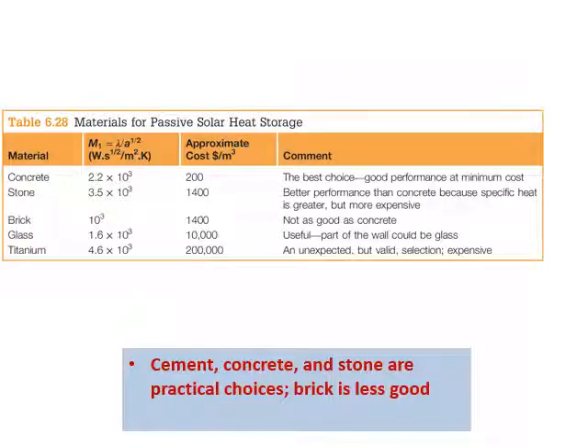And of course, from the previous objectives, it will be as low cost as possible. So you need to calculate the material index performance for each material, M1, for concrete, stone, brick, glass, and titanium. So the biggest value for the material index performance will be the titanium. And then the approximate cost, for a fixed density and fixed volume, over here concrete costs like $200 per meter cubic, it's very cheap, and then stone is $1,400 per meter cubic, and the brick is also 1,400 per meter cubic, and glass is 10,000 per meter cubic, and then the titanium, which is 200,000 per meter cubic.